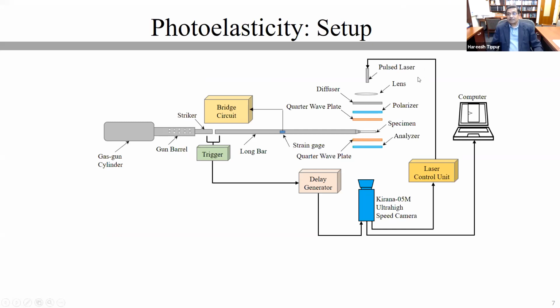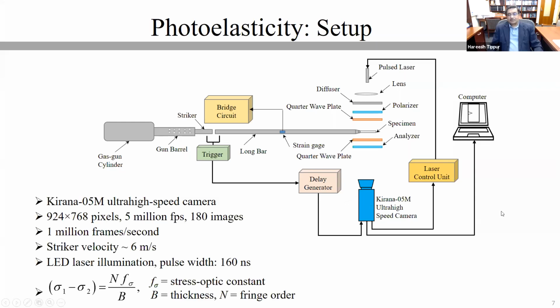It has a pulse laser, which produces laser pulses about 160 nanoseconds long and repeats itself. And the event itself is captured in the form of fringes by a high-speed camera, which is a Kirana high-speed camera. The details of that high-speed camera are as follows here. It is a fixed resolution camera, 900 by 800 pixels approximately. It can run up to 5 million frames per second and can capture about 180 images at that resolution. All our experiments were done at 1 million frames per second.